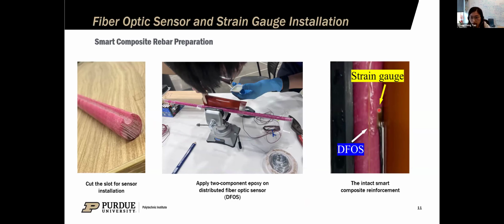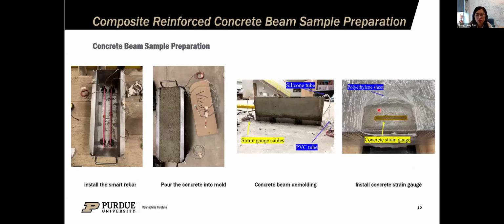Before we put the smart rebar into the concrete, we want to make sure the sensors are installed well and the signals can be captured successfully. And then after the fiber optic sensors and strain gauges were installed, we made reinforced concrete beam samples using the mold. So we fixed the composite rebar using the rebar chair here before pouring the concrete.